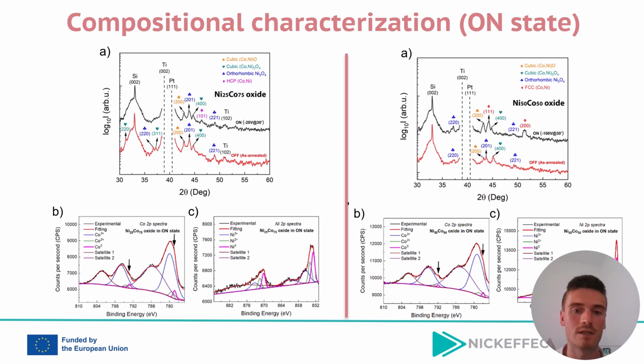In the case of the most cobalt-rich composition, the 101 peak corresponding to the dissolved cobalt-nickel hexagonal close pack phase arose.